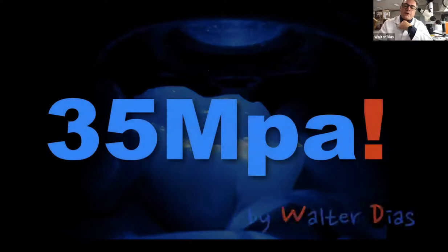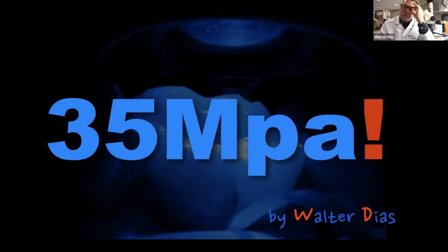Today with the modern adhesives, we are already reaching up to 35 megapascal. This is equivalent to almost 3,500 kilos on one square centimeter. So imagine a small little square centimeter and you can have 3,000 kilos held by the adhesive, that gives you 35 megapascal. This is a very interesting and very powerful technology that we have in our hands today.